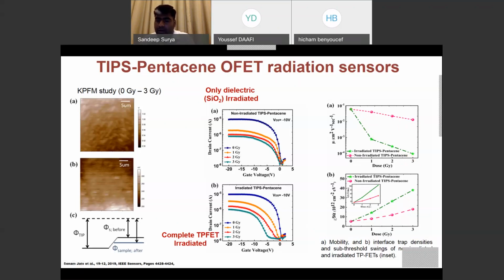Similarly, the density of interface traps has been calculated from the sub-threshold swing, the inset that I've shown here. The green part corresponds to the TIPS-Pentacene irradiated device and the pink corresponds to the non-irradiated device. By making use of the sub-threshold swing, we calculated the density of interfacial traps, and again you see the same change. Thus, essentially what we conclude from this study is that it's not just the dielectric that is important in identifying sensors related to radiation. There is also a crucial role of TIPS-Pentacene organic semiconductors in increasing the sensitivity of these devices.